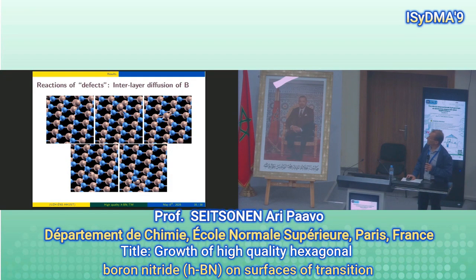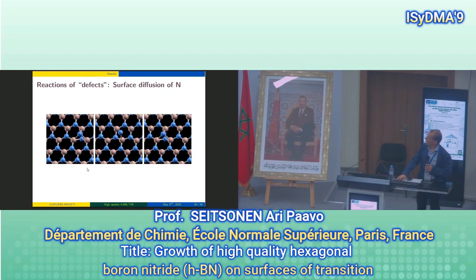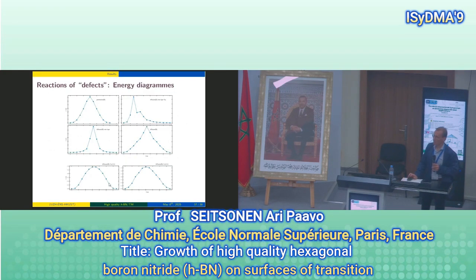And this would be just the very last example. Here we have the initial state of the diffusion reaction: this boron adatom, which stands on the nitrogen. This is now without the substrate still, and then how it goes along the reaction path. Here it's penetrating the hBN layer, and then here it's beneath. You don't see it, but the atom goes beneath. So this is the energy. We calculate the energy path and the energy for this reaction of penetration. And then this would be another reaction, and we can derive these reaction energies. This is ongoing work, and as I said, we have started the same on the substrate. So this is on copper 111. This is the freestanding one. So we can study these reactions.